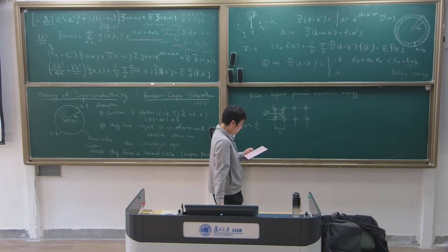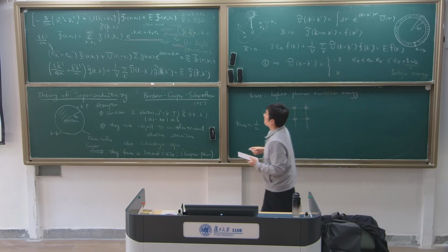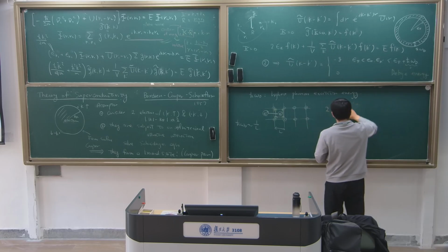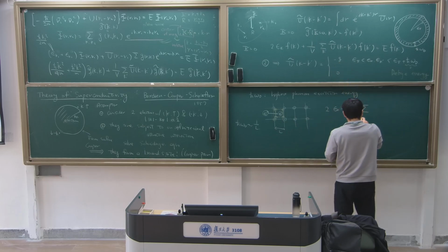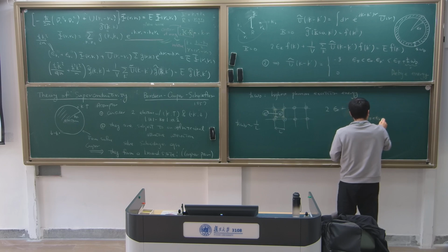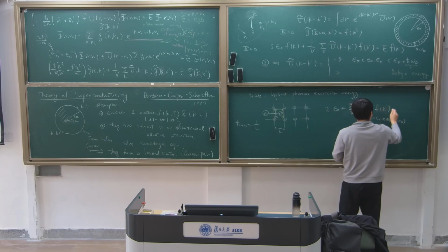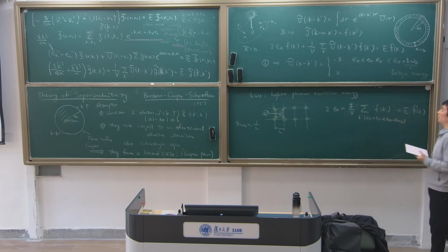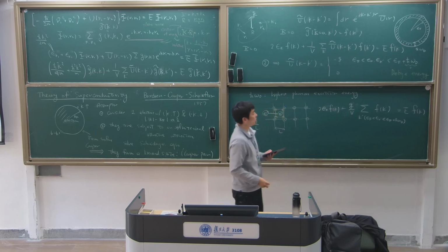And then we will try to solve this equation. If you assume this potential, then this Schrödinger equation can be written as follows. Now it's just a constant, and we just need to sum over K prime, where K prime is from the Fermi surface to the Fermi surface plus H bar omega D. That's the summation range. This equals E times F of K. That's the Schrödinger equation. Oh, sorry, I missed the F of K. So that's what you get.